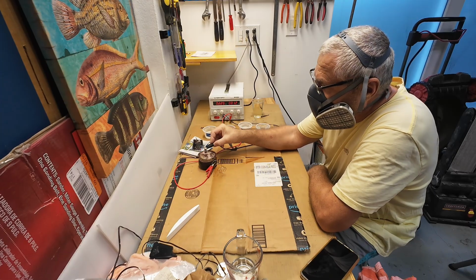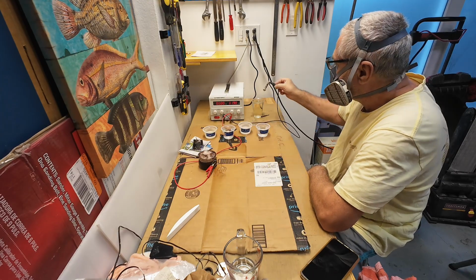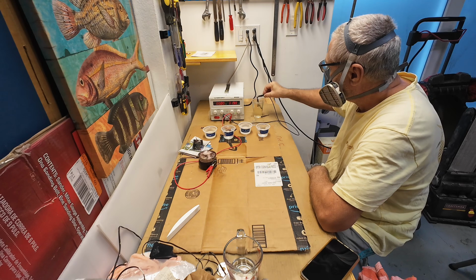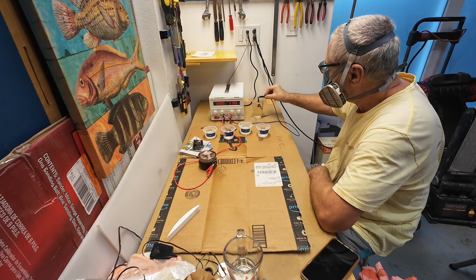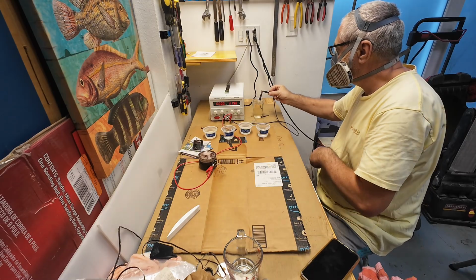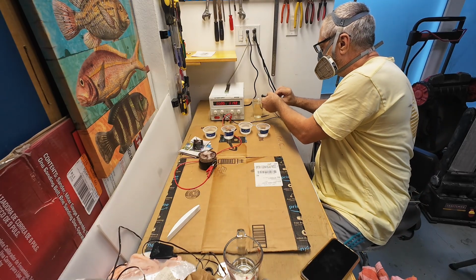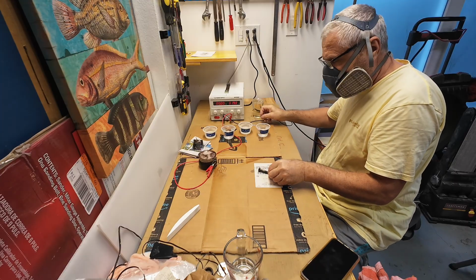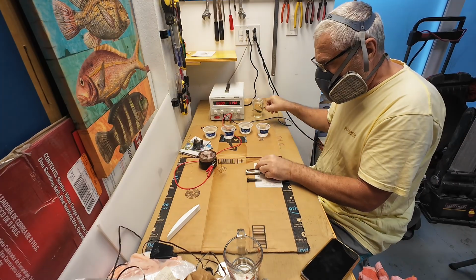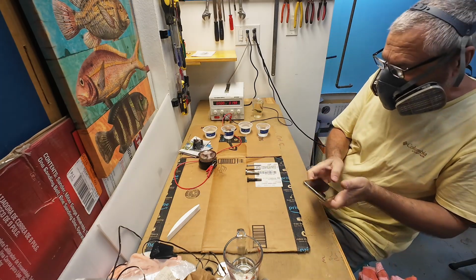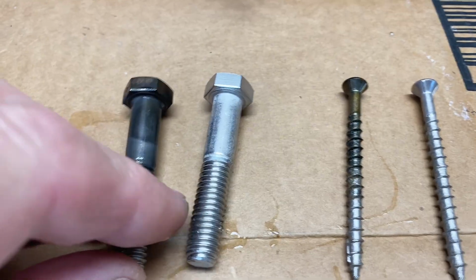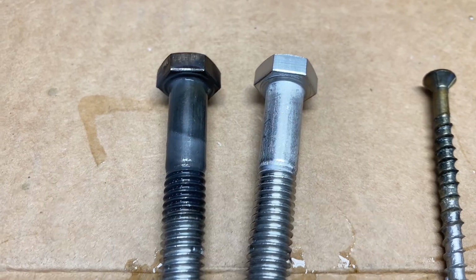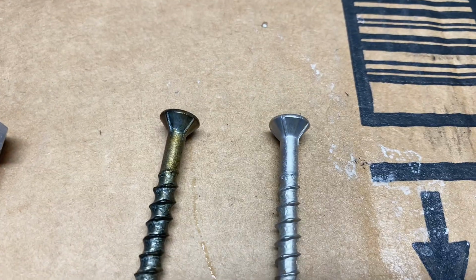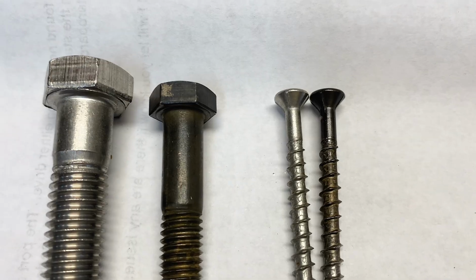Now I can try applying the coating to some old bolts and screws to determine the optimal amount of time. The first time I keep the bolt and screw in the bath for 15 minutes. The second time for 30. The coating comes out black, but it polished beautifully to a mirror finish. Here are the results of the first and second trials.